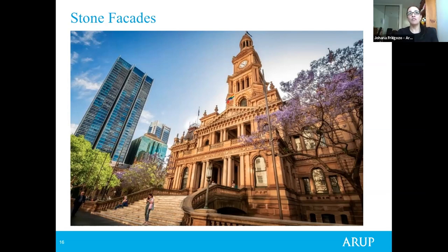The principal elements of a stone facade are the type and quality of the natural stone, the alignment of the units, the tightness of the joints, the use of adequate joint material, and the different types and conditions of anchorage and support. Some of the common defects in stone are obviously cracking, and cracking sometimes could be due to imperfections in the stone itself, or concentration of vertical stresses due to non-uniform transmission of loads from above, or excessive movement of supporting elements, or corrosion of the steel behind the panels or anchoring elements.